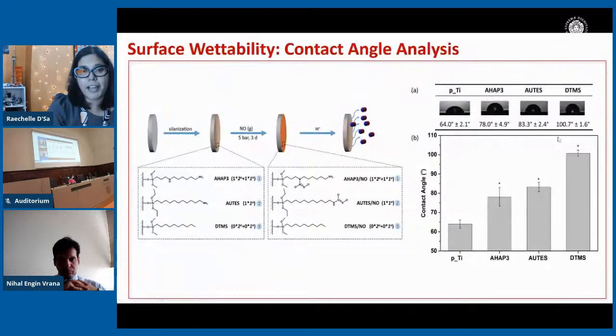So we followed each step of the reaction, initially using contact angle analysis. What you can see here is that Miley took the titanium surfaces, polished them, and then immobilized the different silanes on the surface: the AHAP, which has the 2 amino groups, the AUTES, which has just the terminal amino group, and the DTMS, which has no amino group. We then exposed the amino functionalized surfaces to nitric oxide gas under high pressure for 3 days and tethered nitric oxide onto the surfaces. Over here, it should tether in 2 possible positions. Over here, 1 position, and over here, it shouldn't tether onto it at all.